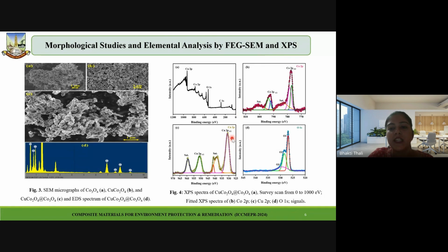Further, Figure 4C is of copper 2p. Copper 2p gives two prominent peaks, copper 2p 3/2 at 931 electron volt and copper 2p 1/2 at 951 electron volt, which confirms that copper is present in the +2 oxidation state. Along with that, there are two satellite peaks for the same. Oxygen 1s is deconvoluted into three peaks, 527, 529, and 531 electron volt respectively, corresponding to the metal oxygen bonding which has taken place, specifically copper oxygen and cobalt oxygen.